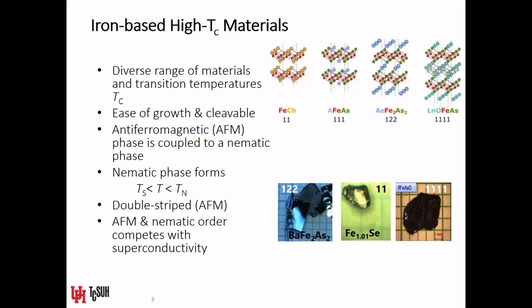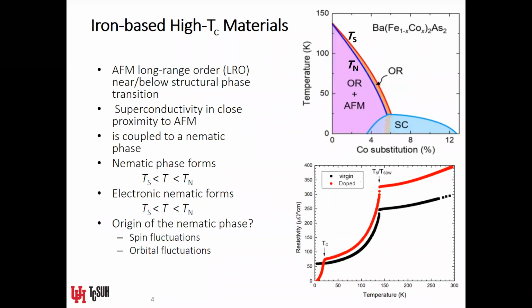Another important thing about the iron-based high T_Cs is that the antiferromagnetism has a striped variety, meaning that there is a spin density wave, or an anisotropic arrangement of magnetic moments within the plane of the iron layer along the A and B axes. So typically there's a double-striped antiferromagnetic ordering within these materials. And finally, we have to note that the antiferromagnetism and the nematic order are thought to compete with superconductivity.